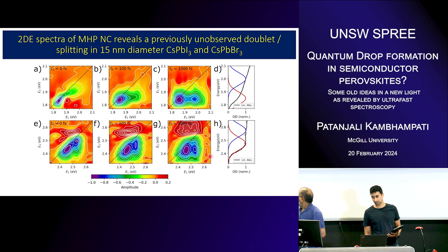That is the challenge. And all of 2D spectroscopy has been working at red wavelengths for technical reasons. And it was easier. And also because the 2D spectroscopy field had been largely led by people who were looking at photosynthetic reaction centers, which absorb in the red. So that was 600 nanometers. We had to go to 500 nanometers, where the perovskites are. So 450 to 550 nanometers, roughly, is our bandwidth right now.